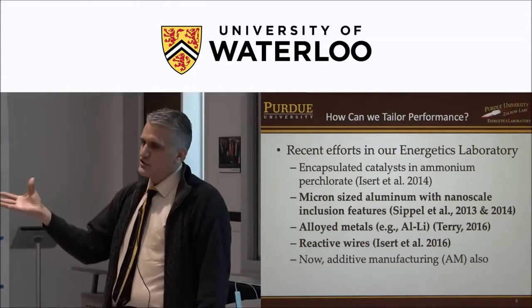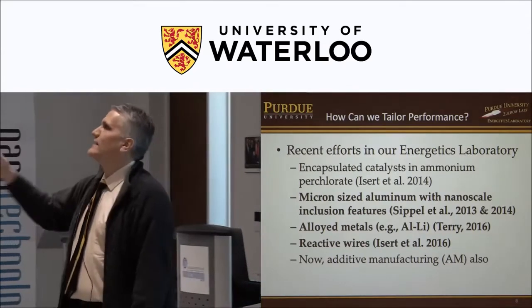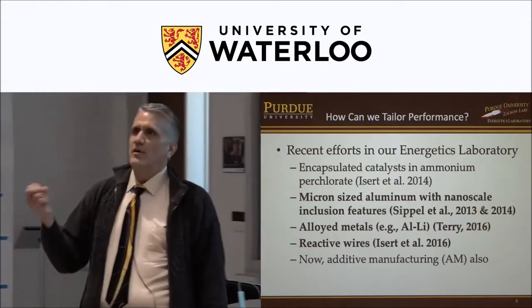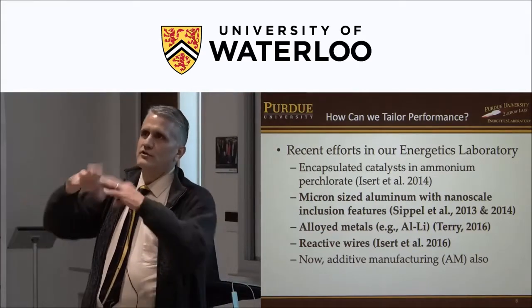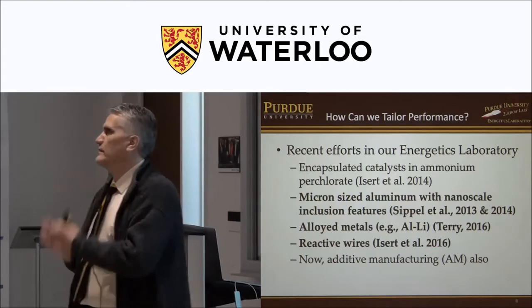We have that in our solvent. We dissolve the ammonium perchlorate. We add in an anti-solvent, and those nanoparticles act as nucleation sites for the crystal growth. So the crystals grow around the catalyst.